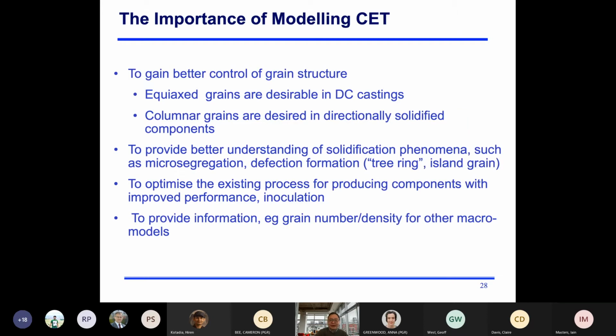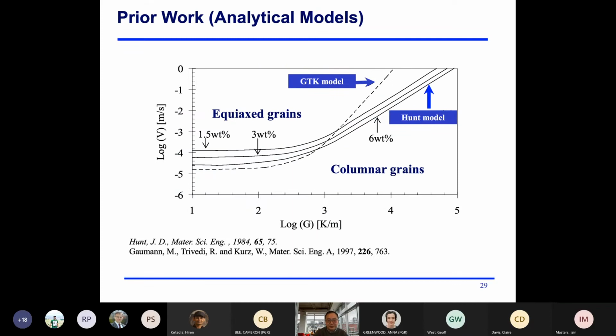So we try to go a bit deeper by doing what we call a solute-driven solidification modeling, to look into how this grain structure can be changed, or how you can control grain structure to be either columnar or equiaxed grains. This is a well-established theory looking at the effect of growth velocity on this axis, and thermal gradient on the horizontal axis. So this we call a CET map.